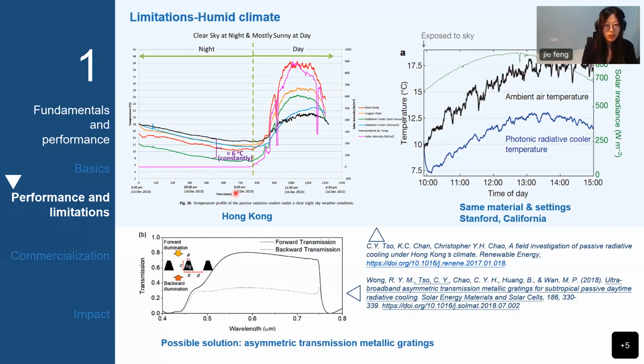This is mainly believed to be caused by the high ambient radiation in cities with humid climate, and therefore we need to consider the specific climate, which can be a limitation to the performance of the materials. And one possible solution for this humid climate is this asymmetric transmission window. You can see it has different transmittance for the forward light and the backward light. If we allow the emission to go out, but block the certain part of the incoming long wave radiation, it can eliminate the side effect of the humid climate to a large extent.